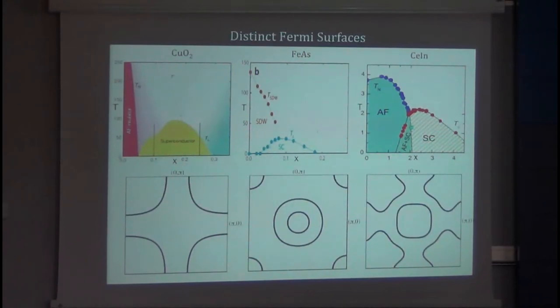But if you look at the Fermi surfaces, these are very, very different materials. Really different. One has a nice hole-like Fermi surface. Another one has between 3 and 5 Fermi surfaces, some hole-like and some electron-like. Heavy fermion Fermi surfaces are themselves very complicated beasts. Cerium cobalt indium 5 has at least 2. So in terms of the Fermi surfaces, they look like very different problems.